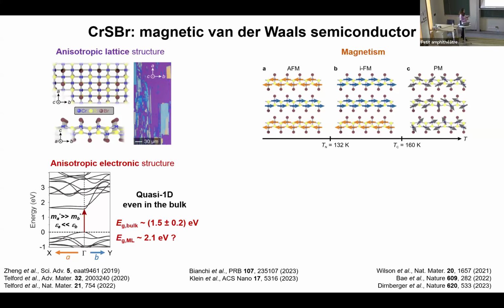The band gap of CrSBr is around 1.5 electron volts in the bulk regime. And theoretically, it has been predicted that the monolayer band gap should be around 2 electron volts. And I have to mention that chromium sulfide bromide remains a direct band gap semiconductor down to the monolayer.